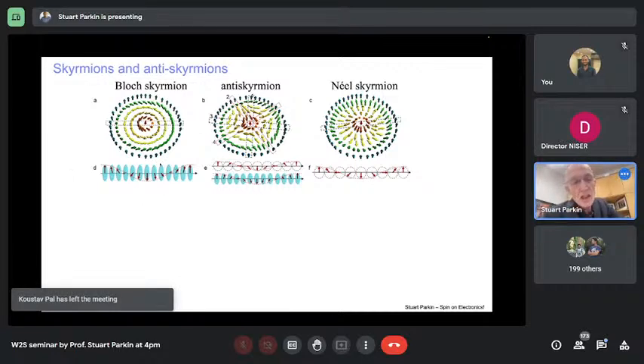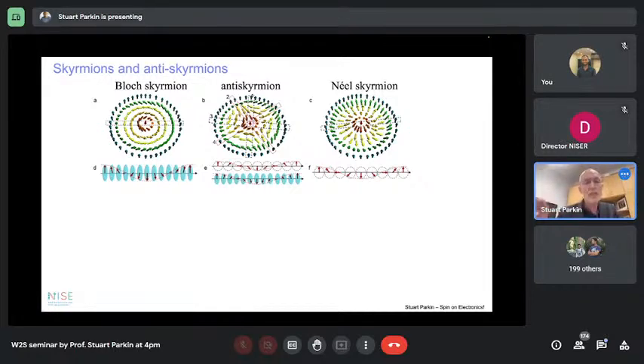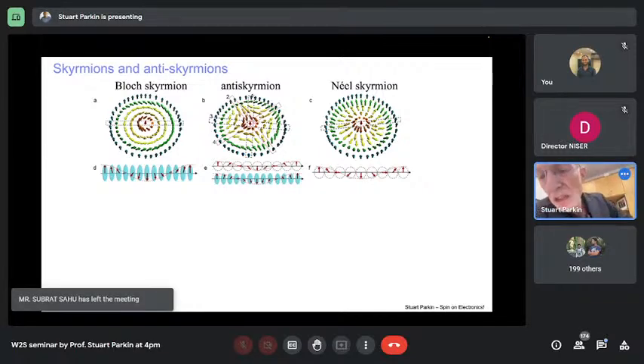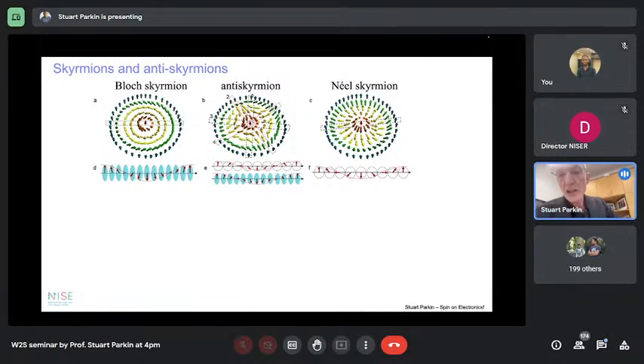And if you look carefully, I hope you can see that when the magnetization outside this circle is pointing up, in the very middle of this circular object, it's pointing down. And if you go along a radius, you can see that the magnetization rotates in the plane perpendicular to the radius. That's a Bloch skyrmion. On the right-hand side, you can see a Néel skyrmion. In this case, the magnetization rotates from an up to a down direction along the radius, but by rotating in a plane parallel to the radius. This type of Néel wall is exactly the same as in the racetrack that I was briefly discussing.